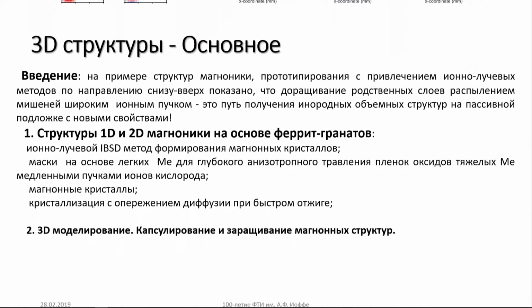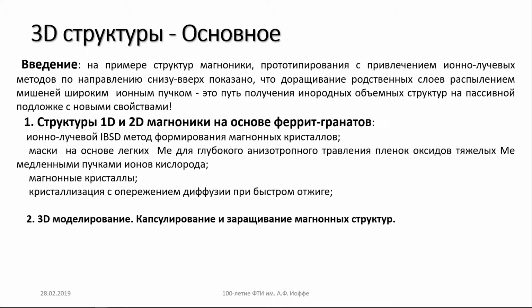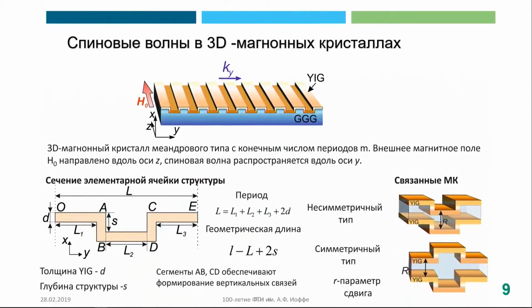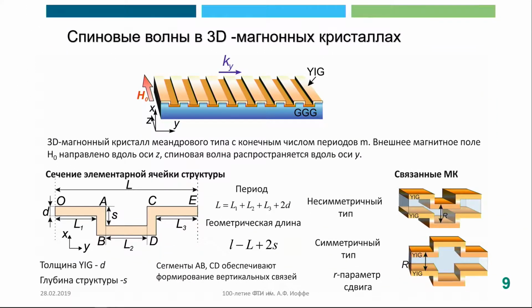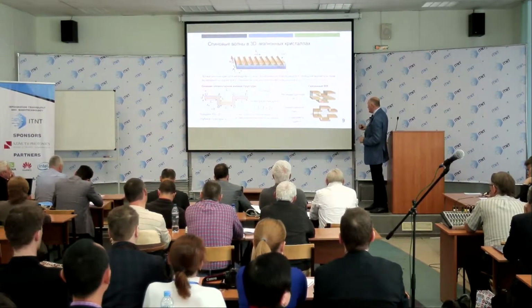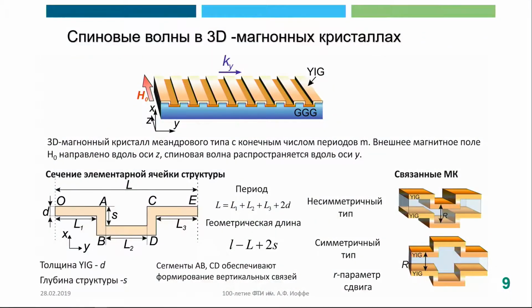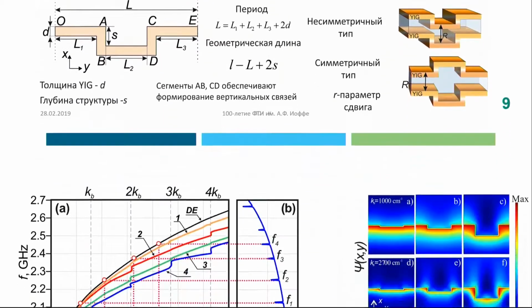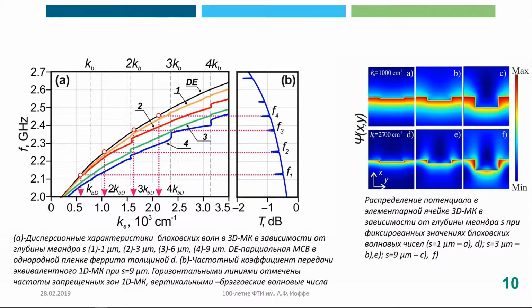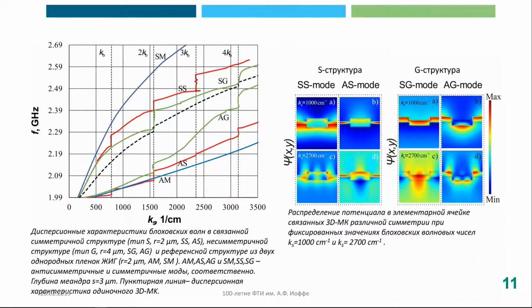As I already said, it's possible to create three-dimensional structures, and they really have the shape of a film in three dimensions. Considering that the waveguide is also restricted in that direction, we excite a wave which goes in this direction, then goes down, again in this direction, and so on. Then you can make nets of these magnetic films in three dimensions, and we can relate one film with its topology in three dimensions to another film, and so on. These are experimental results showing that this is really possible, and some typical structures which we prepared are these three-dimensional structures.